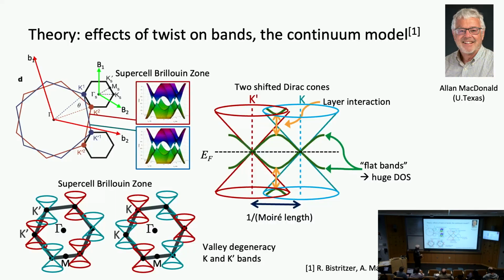And you can tell from this very simple picture the distance between the points of the Dirac cones scales as 1 over the Moiré length. The Moiré length, of course, is inverse to the twist angle. So this distance is proportional to the twist angle. The smaller and smaller the twist angle, the closer and closer the Dirac cones come together. And by this layer interaction and pushing these Dirac cones together, you get flat bands.